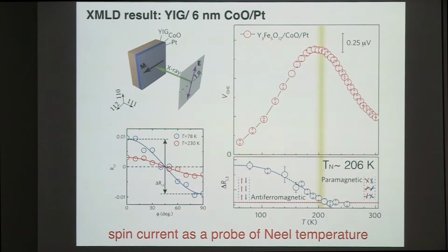So by this, we think we can unambiguously say that this peak is very close to or right at the Néel temperature. This work does tell you that spin current can serve as a probe of the Néel order of the system. If you want to know the Néel order of your sample, you just put it on some YIG or some ferromagnet and detect the spin pumping signal. Somehow it will give you the result.